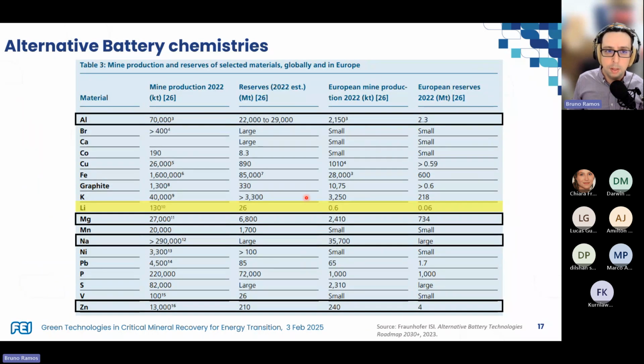So this chart shows a bit on the production in 2022 and the reserves that they had worldwide in the first two columns, and in Europe, especially, in the last two columns of all these minerals. So lithium, for example: the mine production in 2022 was about 130 kilotons, and the reserves are predicted to be 26 million tons. And in Europe, especially, you can see that this number goes way down. So again, 0.6 kiloton production, and the reserves are predicted to be 0.06, so it's quite small. So for Europe, it would be very strategic to move away from lithium.